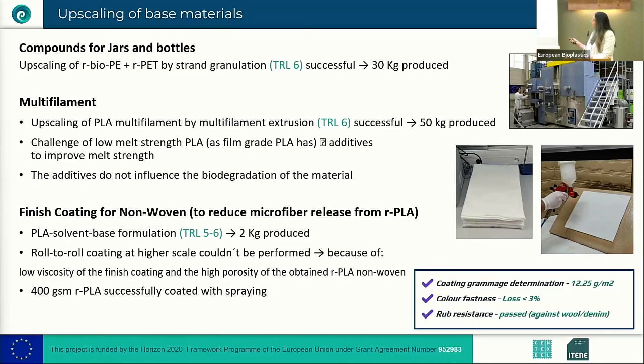From the PLA stream, we also worked with multifilaments and successfully produced 50 kilograms of these multifilaments. The challenge here was that the low melt strength of PLA must be overcome to have a stable production, and therefore some additivation was done, but it still didn't affect the biodegradability of these materials. Another thing that we